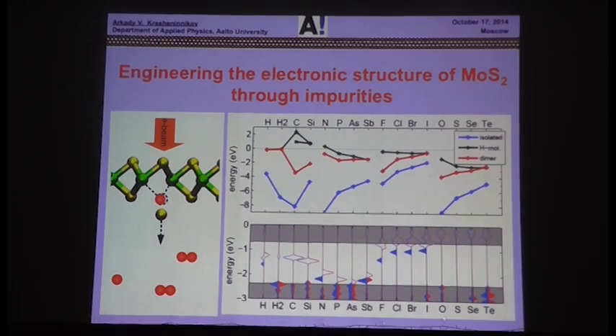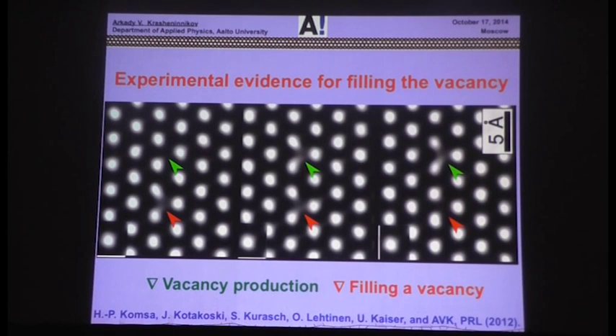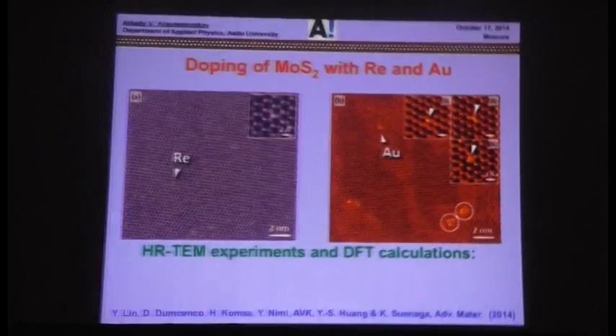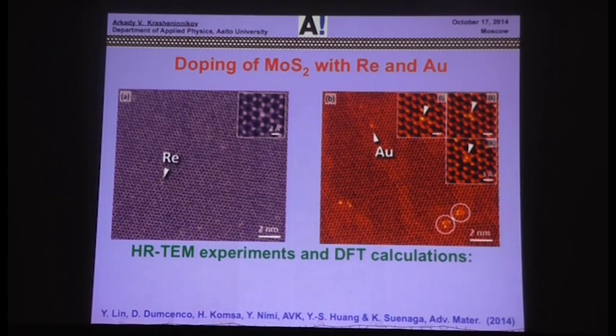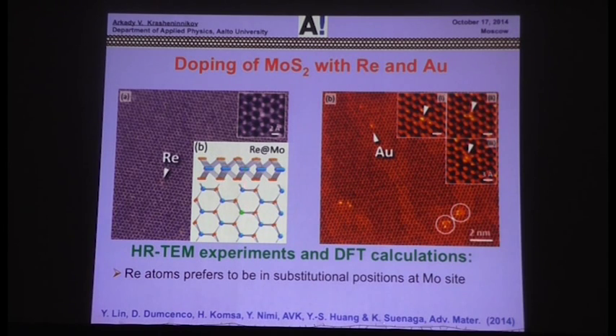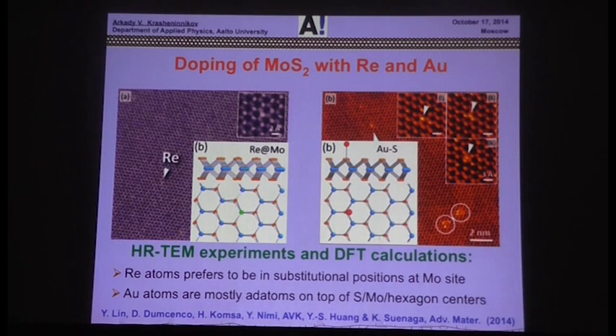But in principle, this works. Dmitry demonstrated it many times, and this definitely happens in reality. In this case, you see how a vacancy disappeared, but it is difficult to say if it was another sulfur atom in moly disulfide or something else. Another approach is to grow doped materials. Here, in collaboration with K. Suenaga's group, they characterized samples with rhenium impurities. According to our calculations, rhenium takes the position of a molybdenum atom, a substitutional impurity, and they also had gold-doped moly disulfide. Gold seems to be on the surface, and in general it tends to make small clusters like here, and the behavior is more complicated.